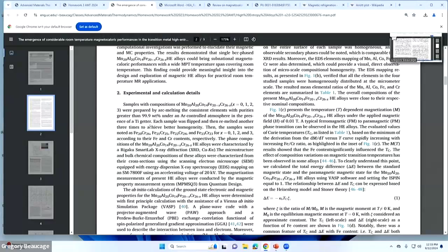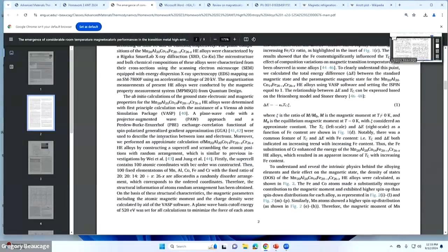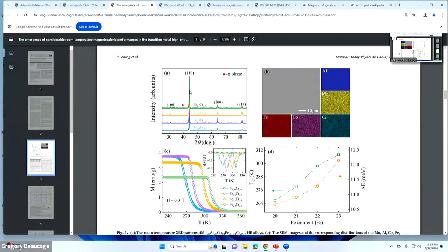So these are almost all transition metals, and if you look at their atomic sizes, they're almost exactly the same size. So they can swap sites in a BCC lattice, which is like simple cubic, but with an atom in the middle, right? So it's a pretty simple crystal lattice. Even though it's a complex mixture, the diffraction from it just has 3 peaks. It's got a weak 100, and these other peaks. No matter what the mixture of the alloy, you get the same positions, so the lattice spacing of the crystal remains the same.